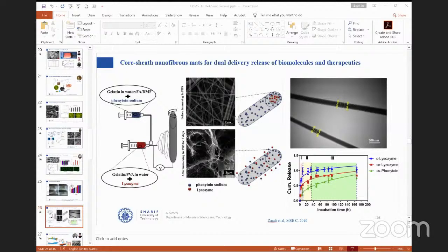As you see here in the TEM structure, we were successful to incorporate and to manufacture the core-shell structure. And in the downside graph, I show the release rate of our growth factor and also the drug versus time. As you see, it is possible to control the release rate, and the burst release is very small because it's a multi-layer. I would like to add that without the core-shell structure, and incorporation of nanoparticles inside, it is not possible really to control the drug release over a long time period.